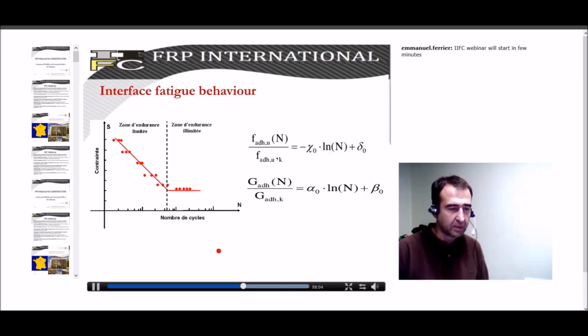At the end, when the fatigue issue is concerned, what we are interested in is to get the ultimate strength of the material, depending on the number of cycles. And for designers, for engineers, this value is interesting to know what is the limit of the stress you should have on the FRP to avoid any fatigue debonding. In this case, in literature, you have some equations such as this one, like Wöhler curves, that propose some constants, of course, depending on the process and the system you are studying. There are not so many, but there are some proposals allowing to know about the fatigue behavior.